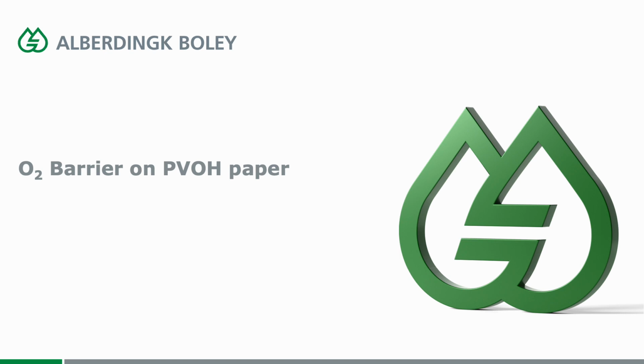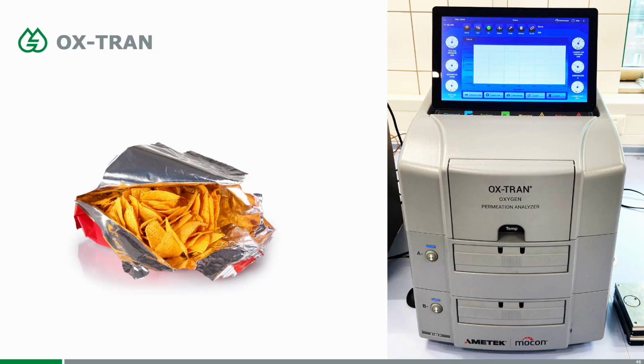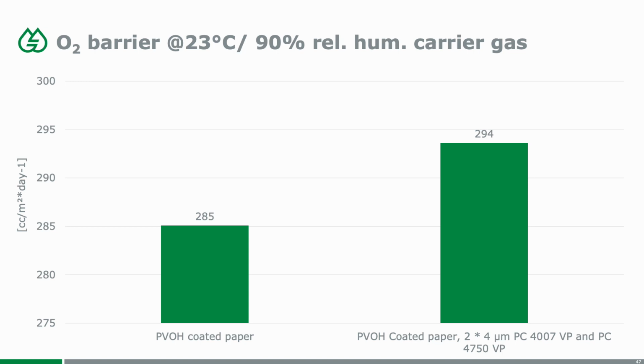Another important factor in barriers is barriers against oxygen, and as you probably know, acrylics are not really offering inherent barriers against oxygen, so you have to find other ways to make these barriers. And in this case we will look at a PVOH coated paper which has a very good oxygen barrier, and we measure that using an Oxtran machine. But the PVOH is a very hydrophilic polymer, and you need to probably protect it against other things to make sure that you have your oxygen barrier, but you're also able to offer a barrier against anything that's water-based.